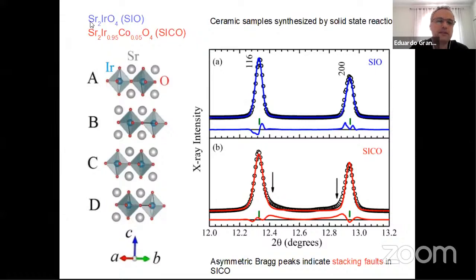As I mentioned before, you have this material, strontium 2, iridium, oxygen 4. And now we make this cobalt substitution. We replace 5% of iridium atoms by cobalt atoms. So we are hopeful that this substitution is still small enough not to disturb too much the crystal structure, but may change electronically the system. That's our hope. But first we checked what happens from the structural point of view.